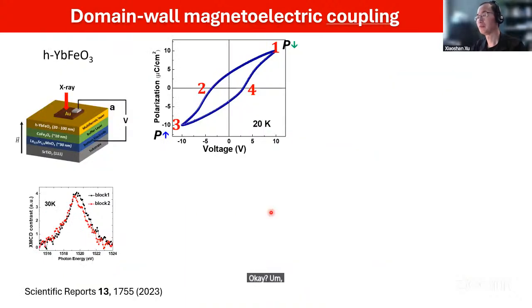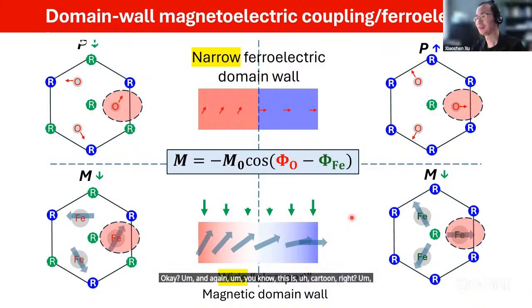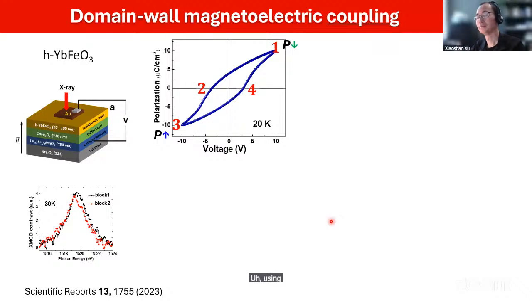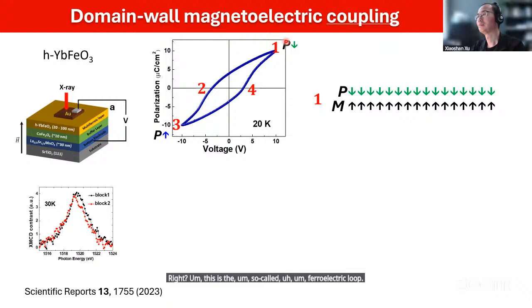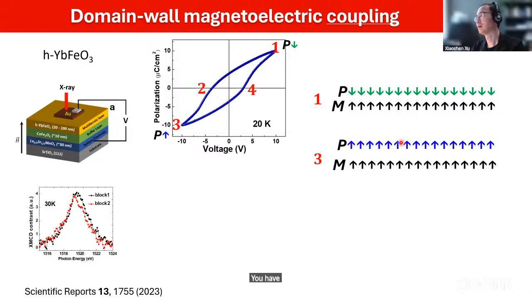And again, this is a cartoon. This is the idea. I want to demonstrate that using our experiment. So the idea is we're going to generate ferroelectric domain walls and see what happens. Remember we showed this, the so-called ferroelectric loop. Here, at point 1, every unit cell has a polarization down. At point 3, every unit cell has polarization up. Because these are unified, the magnetic system is happy because it can follow. If this is homogeneous, the magnetic system can follow as a homogeneous case.